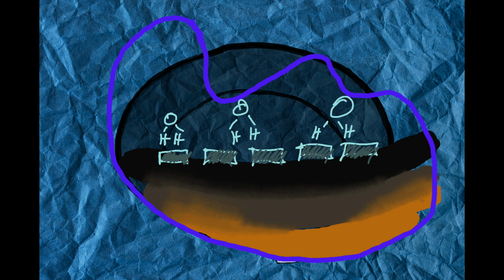Now, common troubleshooting mistakes. Your pan's dirty. You started seasoning and it wasn't clean to begin with, and you may not have had a clean, even surface. It might be an older pan, or you might have sanded it, right? Or got it from the manufacturer and it was dirty. If it's dirty, when you went to apply that thin layer of oil, well, there was crud in it. So how can it polymerize if there was crud in it and that oil can't bond with the surface, right? So always clean your pan.